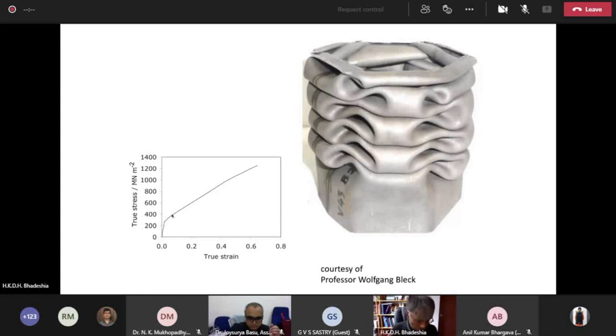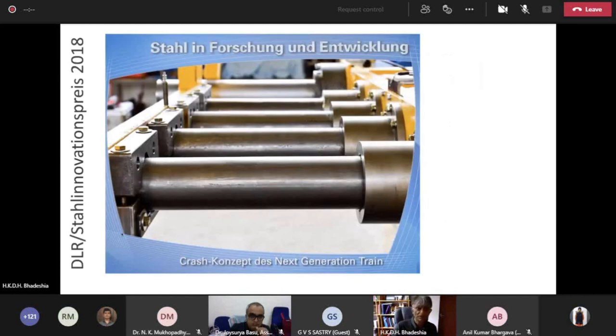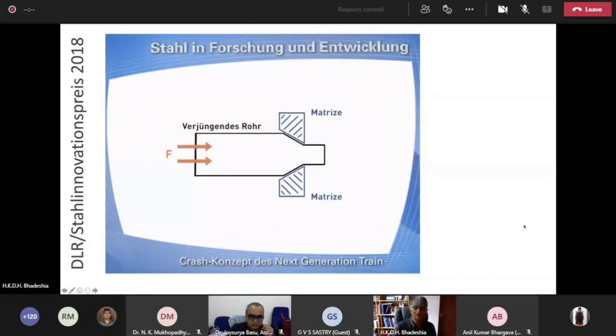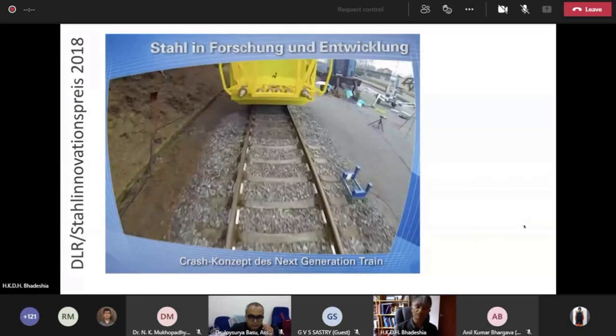Well, this work that I'm going to show you is done in Germany, and it's incredibly innovative. So what they did is design a method so that you get uniform deformation. So these objects here are made from TWIP steel. They are cylinders of TWIP steel, and they're designed so that in a crash, they would become extruded. Okay, so that extrusion gives you uniform deformation throughout the material, and you get much better energy absorption. So I'm going to show you a movie and acknowledge the German rail industry for this. So this is how the TWIP steel is being used to absorb energy in a crash-resistant scenario.